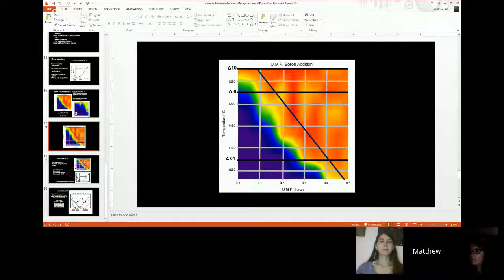when you have too much of those, the glaze becomes physically weak. When you step back and think about it, it makes sense. Silica and alumina are glass formers. They're agnostic as far as chemical durability. As long as they're melting, they're going to be stable. Boron is the same. Boron is also a glass former, so it's inherently stable. But if you have too much lithium, sodium, or potassium, the glaze is weak. And it's weak because of a concept called ion exchange.